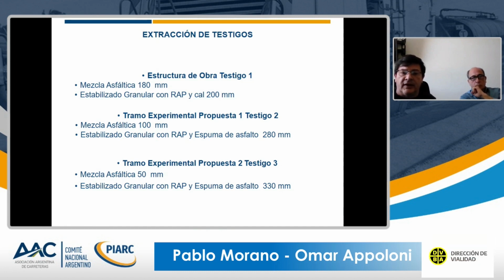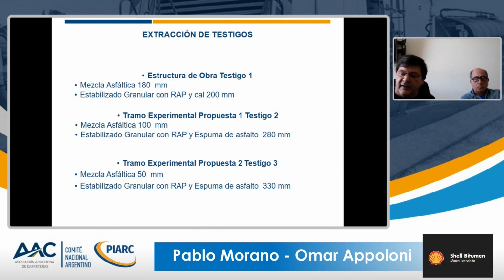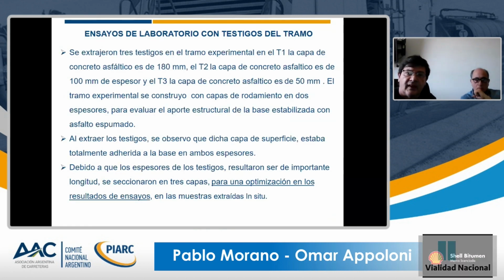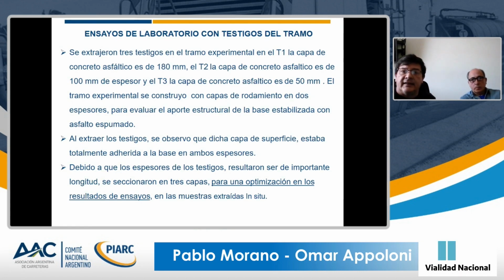And the second stretch, in the manuals, you always found that on granular stabilization with asphalt foam, you could have 50 millimeters of asphalt mix, and that's what we did, but the granular stabilization was 330 millimeters to work in line with the geometry and not alter the parameters and specifications in the bid.